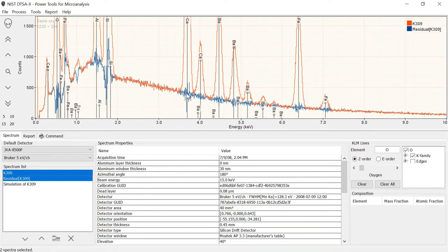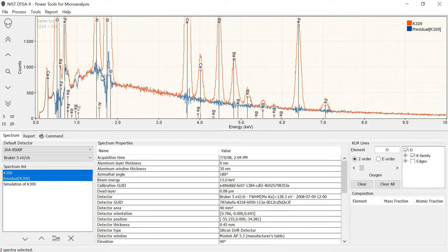In this region, you see that although it's maybe noisy underneath the K line for calcium, on average, it looks very smooth underneath these lines. And that suggests that the fit went well, that we selected the correct elements, and that we didn't miss any elements. If you look over here in silicon, we see that there's a little S curve underneath here. This probably is a result of some sort of chemical shift between the environment of the standard, pure silicon, and the glass.